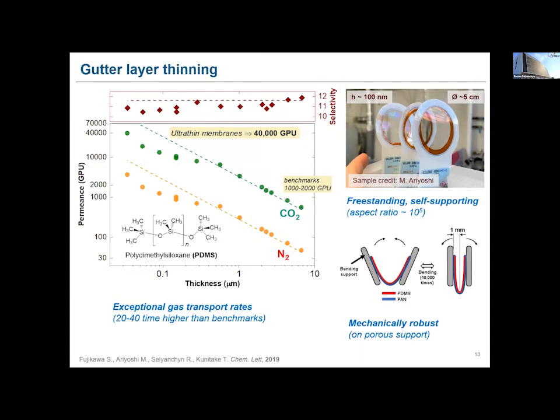For example, by taking one of the most, sorry, the light in my room just gone off. So for example, by taking one of the most widely used material in membrane science, which is polydimethylsiloxane, we were able to fabricate freestanding and defect-free membranes, which are shown in this photo, you can see, with a thickness of much below than 100 nanometers.